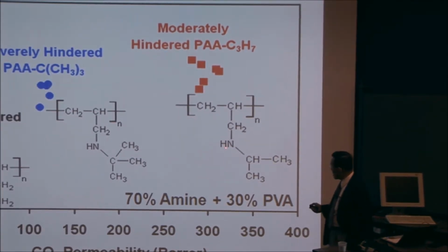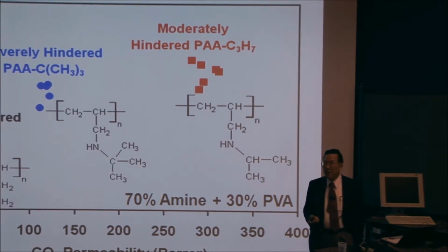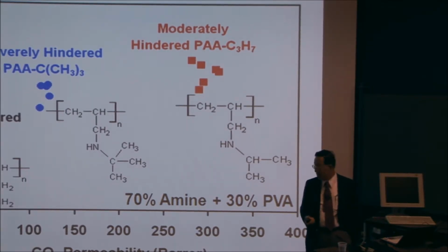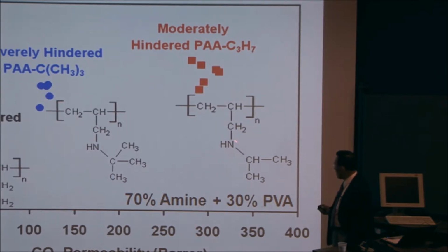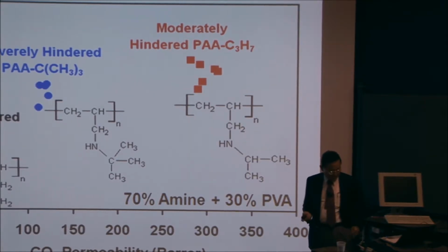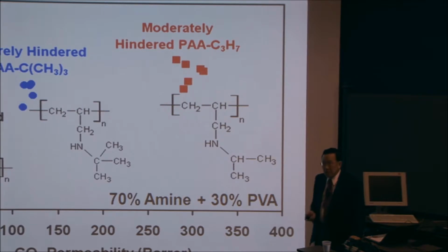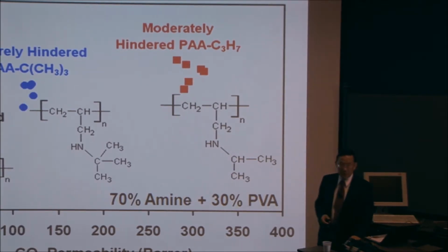So when CO2 attaches to the nitrogen side, you make a so-called carbamate. Okay, because the carbamate is unstable, due to the presence of the bulky group. So this carbamate is then hydrolyzed readily, to form bicarbonate, and that also regenerates this amino group.